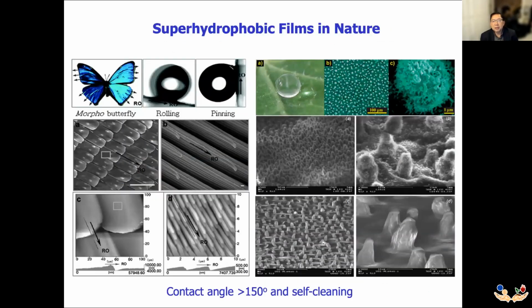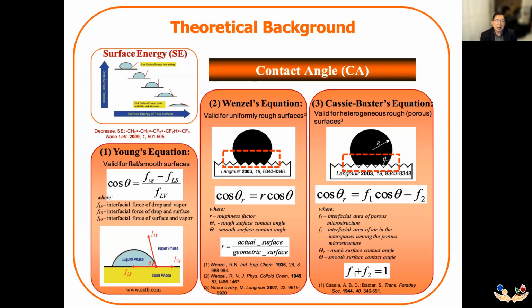Now, when it comes to films in nature, we are very familiar with the hierarchy of structuring and composition in the case of superhydrophobic films, which are naturally resistant to water based on the roughness or scale of roughness and the entrapped air, as in the case of the Cassie-Baxter wetting phenomena. A lot of this can be observed as deviations from the ideal Young's equation, where you have a component of the roughness, which is the regime of the Wenzel equation, or the combination of roughness and trapped air, as in the case of the Cassie-Baxter equation.